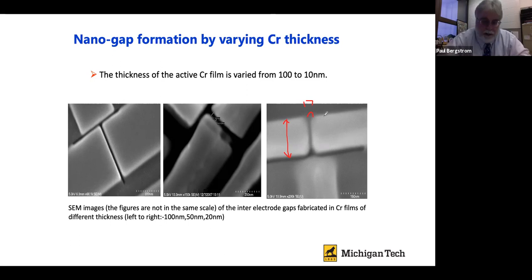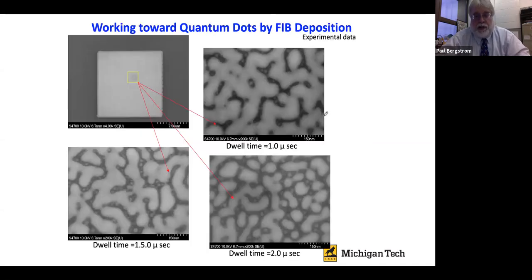So then we said, okay, it's still not small enough. To get room temperature quantum confinement for the quantum dot, we have to be less than 10 nanometers. That allows then for an electron to be trapped on that quantum dot with sufficient energy such that we can transfer it on, store it there, and then transfer it off under the right conditions. So that was our target. So we said, well, okay, we can't do it by etching. So let's think, what can we do by using this focused ion beam by another way?